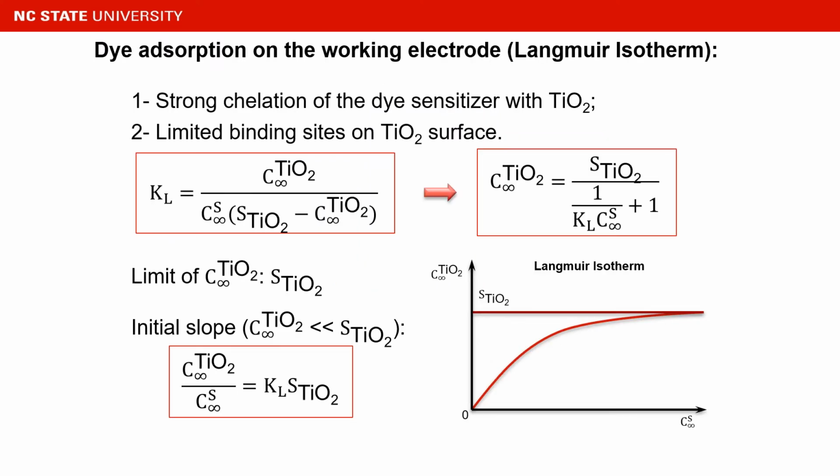The relation between our course and the paper is studying the dye adsorption on the working electrode, which follows the Langmuir isotherm, as it is due to the strong chelation of the dye sensitizer with the titanium oxide and the limited binding sites on the titanium oxide surface.